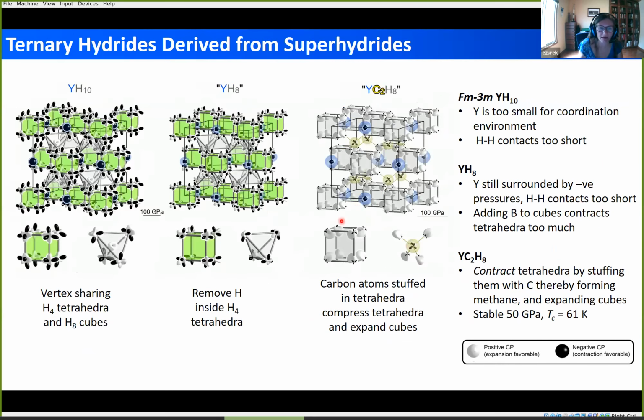Using this way of thinking, we found that in yttrium H10, or the hypothetical yttrium H8, the yttrium is much smaller than lanthanum, so we can't just add a boron atom or another stuffing atom. However, if we add a carbon atom, we contract the carbon-hydrogen distances forming CH4, making the system stable down to about 50 gigapascals with an estimated Tc of 60 Kelvin.